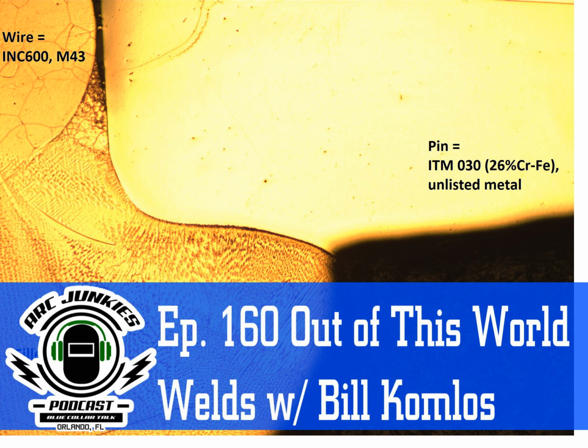Now, because I said earlier it's ferritic stainless, it's 26% chromium. Well, it's virtually all ferrite, okay? There's no nickel in here. Nickel is what they call an austenitizer, and it'll start making austenite grain structures, okay? And in normal carbon steel, we'll have some kind of matrix, and it'll look like leaves, if you will, of the pearlite, for example. You've seen the mock-ups of pearlite where it's cementite on top of ferrite on top of cementite.